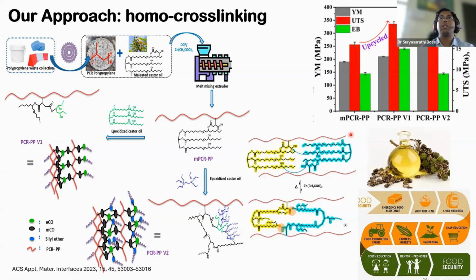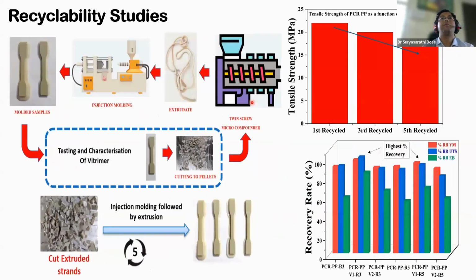Not only that, we were also able to upcycle this material because of the dynamic bonds that you see here. So this is the PCR PP as received, and you can see that in one of the cases, we were able to upcycle both the strength as well as the modulus and also the elongation at break. So this particular oil doesn't degrade during the processing of polyolefins. That is the beauty of it. And this oil actually helps in improving a lot of network connectivity within olefins. And that's the reason why we see a lot of upcycling.